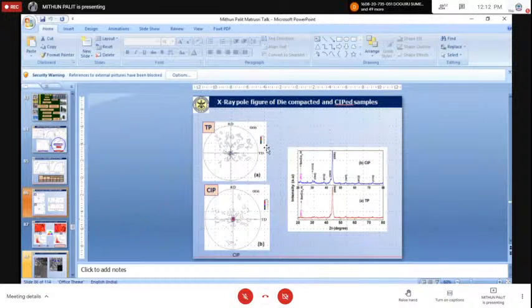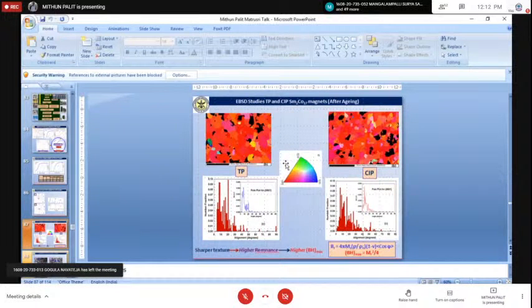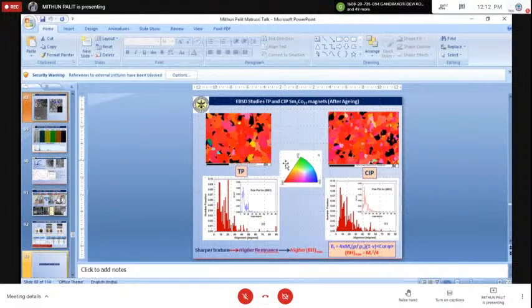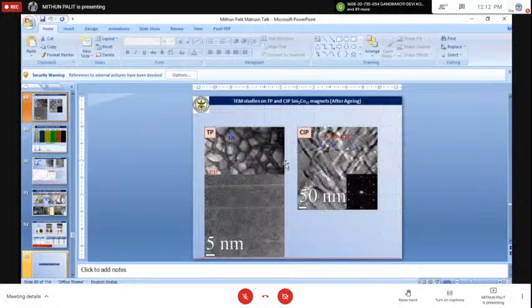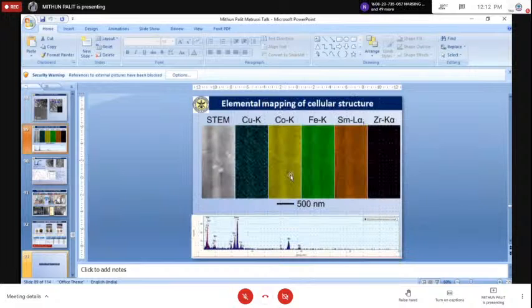And TP, that is the conventionally processed magnet, has some spread, therefore it has less BR. And this orientation you can also see in the microstructure, so I will not go into detail. And these are the pinning precipitates formed in the 217 type system. And here, from the transmission electron micrograph, we can also find out the distribution of elements.